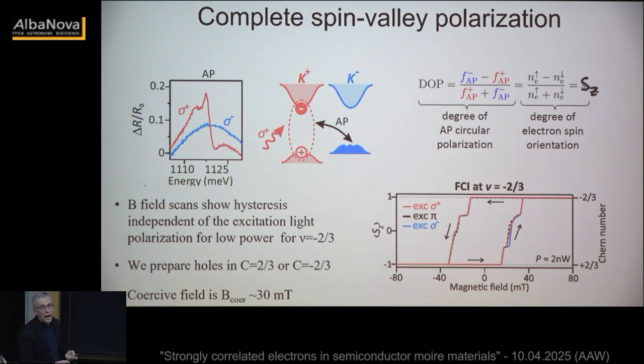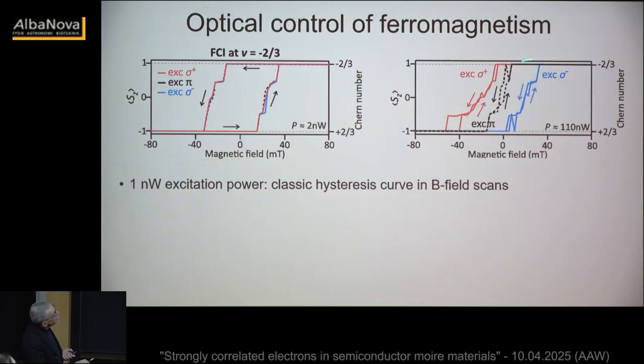All right. So now, if you do a magnetic field scan, instead of measuring the spin susceptibility, what we see is hysteresis, because we're now working at temperatures where the system becomes magnetic, and therefore we have this hysteresis curve. This is at -2/3. And this is at low power, and you see that when we probe optically, we use sigma plus, sigma minus, or linearly polarized, and there is nothing different.